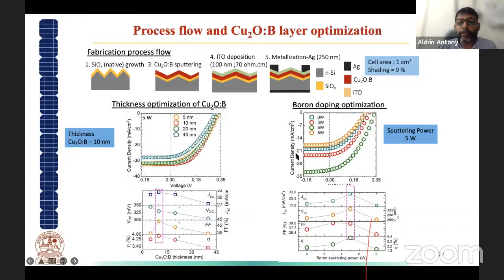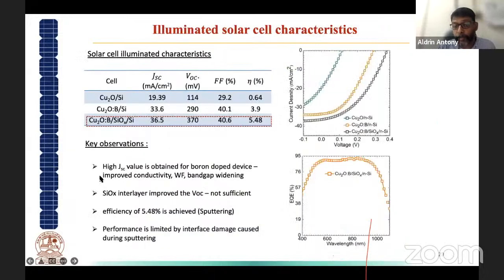And we changed the sputtering power of boron, which changes the doping level. And the optimum power that we have found for the boron, that is, if we increase the power, then the doping concentration will increase. So the optimum power that helps us to get the better IV characteristics is the 5 watt. Okay, so in combination, this 10 nanometer thickness and the 5 watt was used for the other solar cell fabrication. And you could see here, if you are using a 5 watt, all the solar cell parameters, that short circuit current, fill factor, and open circuit voltage are all high. And this is what we chose, 5 watt and 10 nanometer thickness.